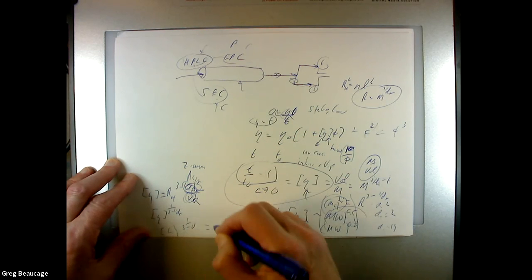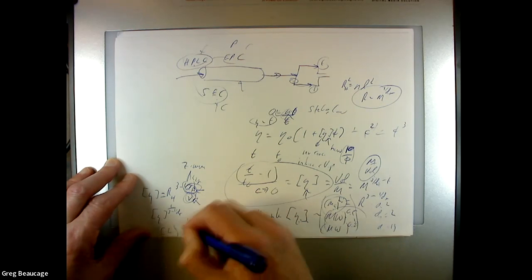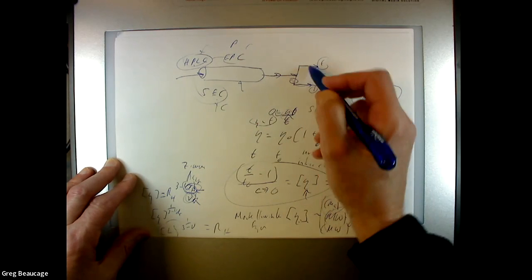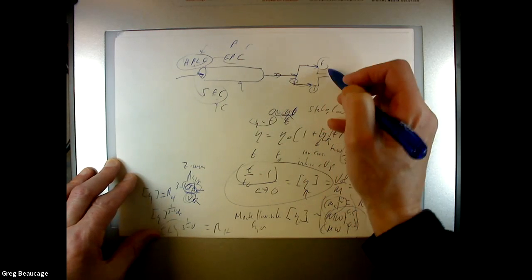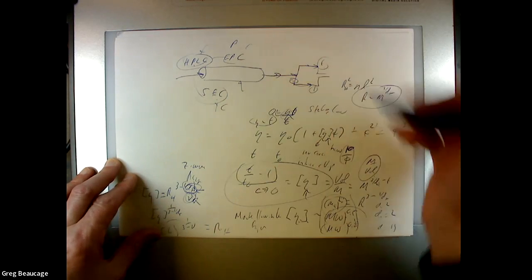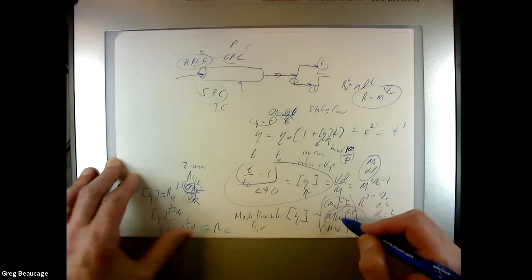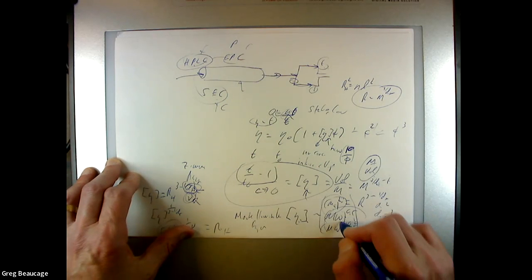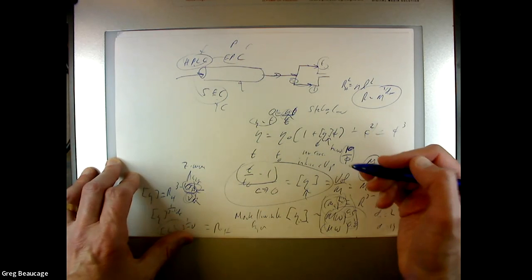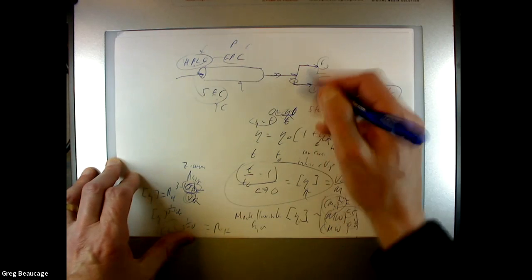So anyway, this intrinsic viscosity, one over that, is going to give you this hydrodynamic radius. If you measure that intrinsic viscosity, which is simple to do, you can do it for each fraction coming out of your column, and you can get the hydrodynamic radius from that. Or you could get the molecular weight from that too, if you knew what this Mark-Houwink coefficient was. Right, so this is kind of a useful thing to do.